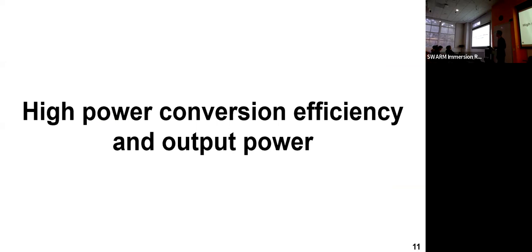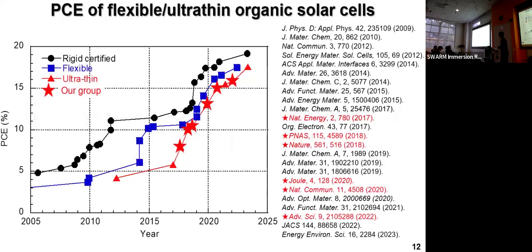The first topic is high power conversion efficiency and output power. Okay. Here I made a summary figure showing the PCE improvement history in the world. I plotted three different color conditions. The black shows the rigid certified PCE of organic solar cells. The recent world best OPV solar cell reached over 19%. Then these blue curves show normal flexible organic solar cells. And this red curve shows the very, very thin, ultra-thin organic solar cells. Typical thickness is less than 10 micrometers. And this star plot represents our studies.